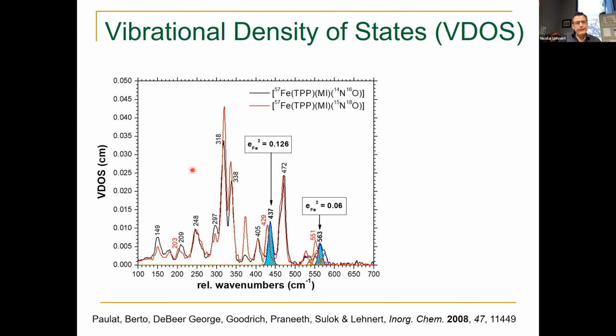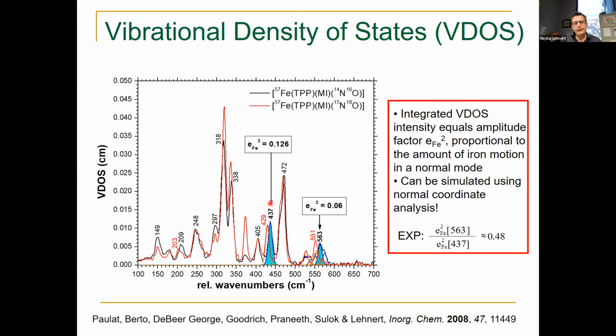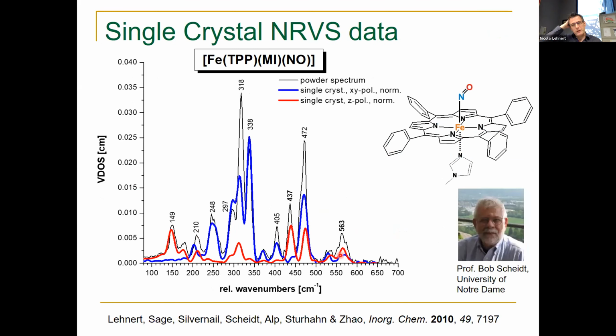And so here is now the same data set transformed into the vibrational density of states. We can now integrate these signals, right? We can calculate the E² factors in this simple way, and we can also now establish that for these two isotope sensitive modes, the relation of the E² factor, so the intensity, is essentially 0.5, and we can use this as a further constraint for data analysis. But in order to really nail the assignments here, just going past just doing a DFT calculation, there were two more things that we did, and the first one I think is still one of the coolest experiments we've done